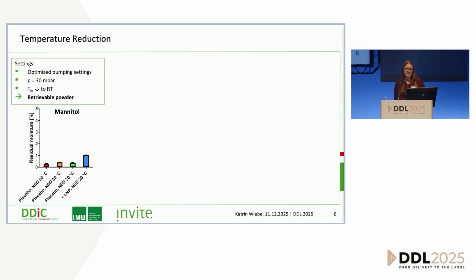The next thing I did was reduce the temperature. How low of a temperature can I use to still produce a powder that I can retrieve? And I did this with mannitol because we had quite some good previous experiments with that. And in fact, I could go down to room temperature with my nanospray drying here and still retrieve a powder that I could scrape off and that I could analyze. And you can see that, for example, for the residual moisture, it doesn't matter how hot the air is that it dries it, and it also doesn't really matter if we add LNPs, the residual moisture is still quite low.